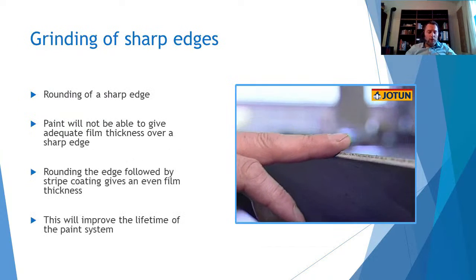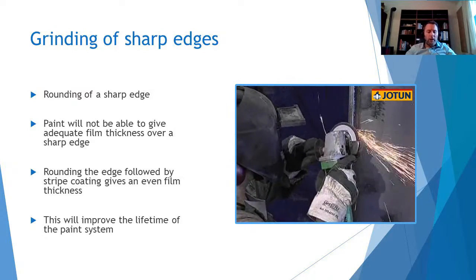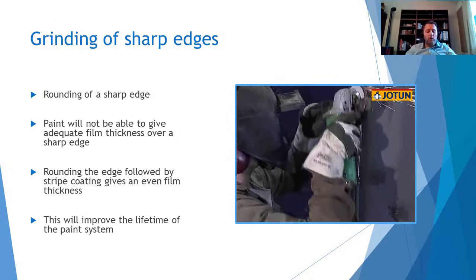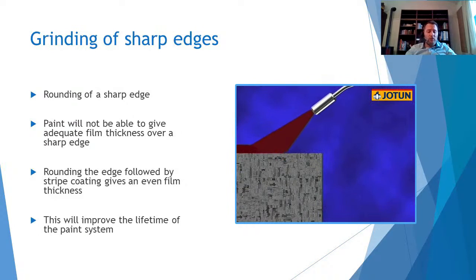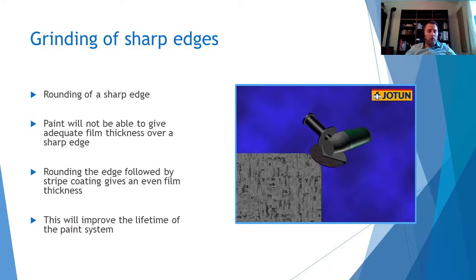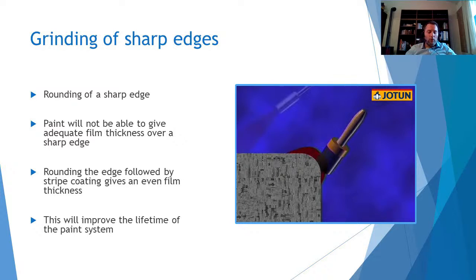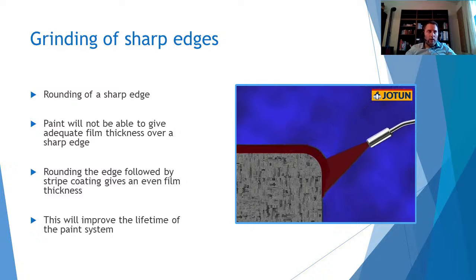Grinding of sharp edges. A typical structure may contain edges that are many linear feet long, most of which have no rounded edge. For aggressive environments, it is mandatory to round a sharp edge, since paint will not be able to give adequate film thickness over it. So, round off sharp edges. Coatings generally tend to shrink and pull back from edges, leaving a thin thickness of protective coating. Stripe coating is strongly recommended when you have to protect a sharp edge or a burr, since it adds thickness to the coating that guarantees long-term corrosion protection.